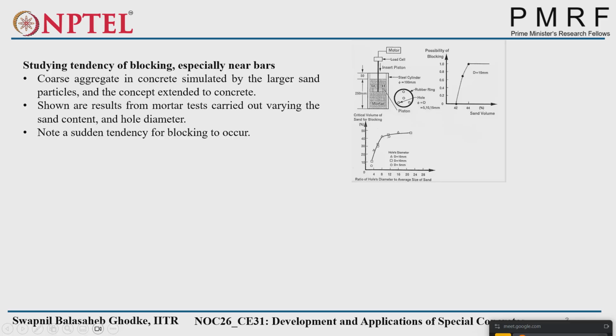We press the piston and we'll see when the mortar is easily flowing through those holes. We can say the amount of fine aggregate or coarse aggregate, especially coarse aggregate, is sufficient, or it's flowable through that mix. When the mortar is not flowing through the piston's holes and it is blocking those holes, that is called the maximum amount, or it is not allowing the concrete or mortar to flow past the coarse aggregates.